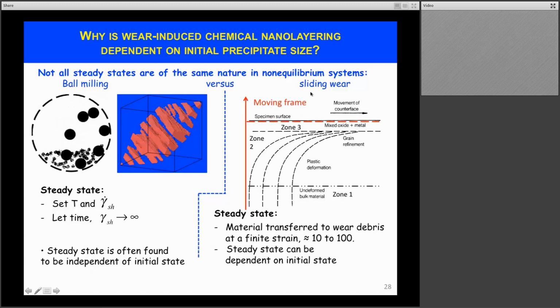However, what I just showed you is that for sliding wear, by changing the size of the silver precipitate, we get different wear response. But this can be better appreciated by realizing that here we have a different type of system where we have a moving frame of reference. Because this material is rising to the wear surface, and at some point is being removed and transferred to wear debris.